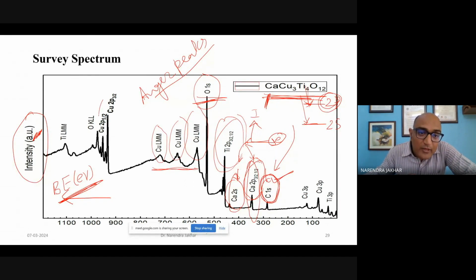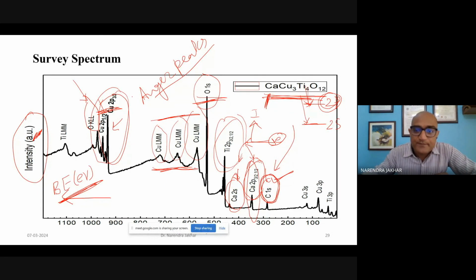So the Cu2p peaks are here. This is Cu2p 3/2, and this is Cu2p 1/2. We have already discussed that Auger peaks have less binding energy than the core level electrons. So the 2p electrons are here, and the Auger peaks are here on the lower binding energy side. So this is oxygen KLL, the Auger peak of oxygen.